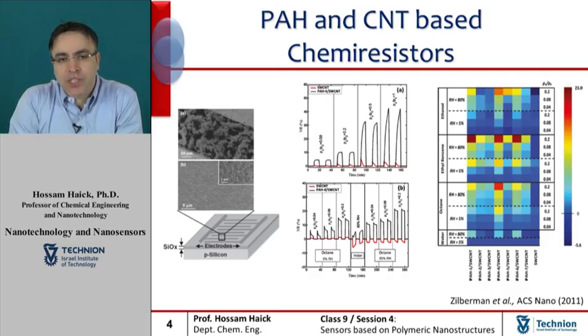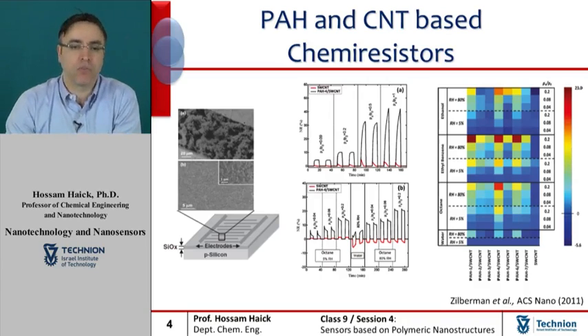Using appropriate combinations of PAH and single-wall carbon nanotube sensors, high sensitivity and highly accurate values can be obtained for discriminating polar and nonpolar VOCs, namely volatile organic compounds, in samples with variable humidity levels that range between 5 to 80% relative humidity. The same array of sensors exhibits self-learning capabilities that facilitated exchanging information about the environmental properties and their observations.